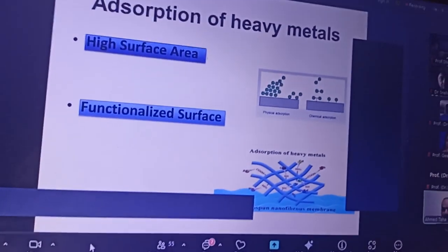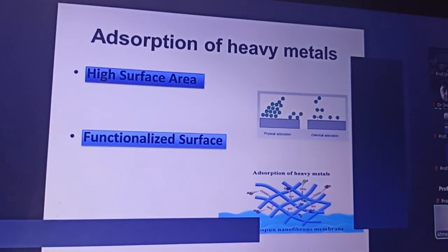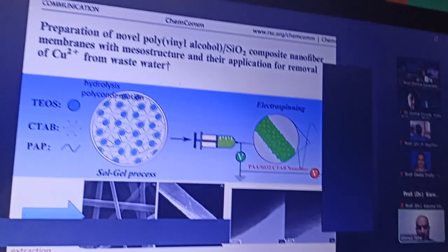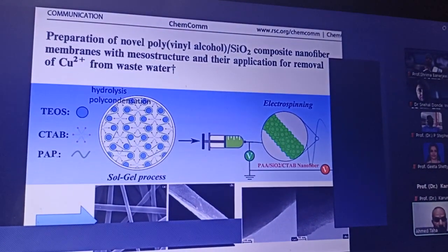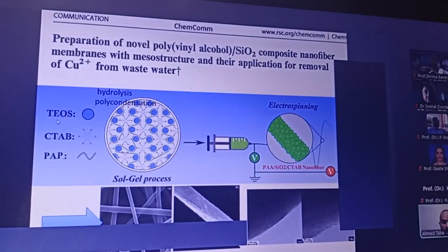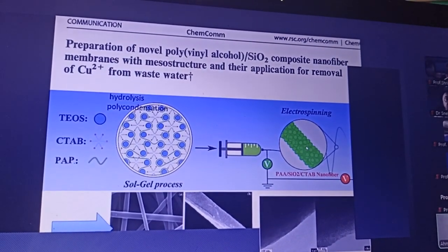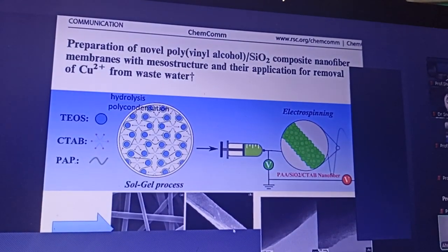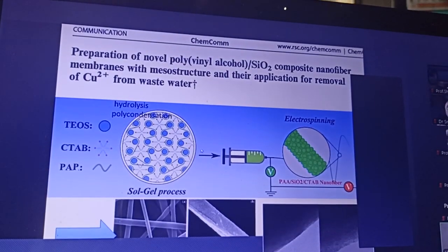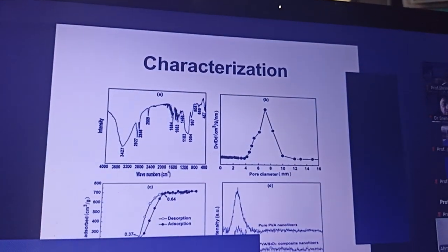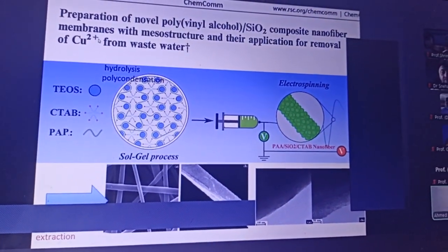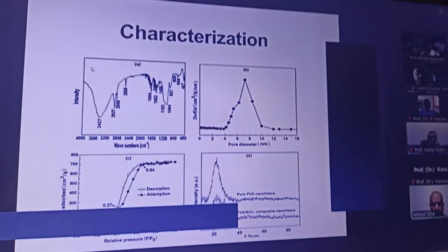So we try to design the membrane with a very high surface area and as many functional groups as we can, to help us catch more of these pollutants or heavy metals. Here is one example of these materials we engineered in our lab. We have the polymer and a template, mix them together, and do the electrospinning, get this product, and do some post-treatment to remove the template. So we have the porous structure and the functional groups that can catch the heavy metal. Then we do the application for copper, for example, one of the toxic heavy metals we can find in water.